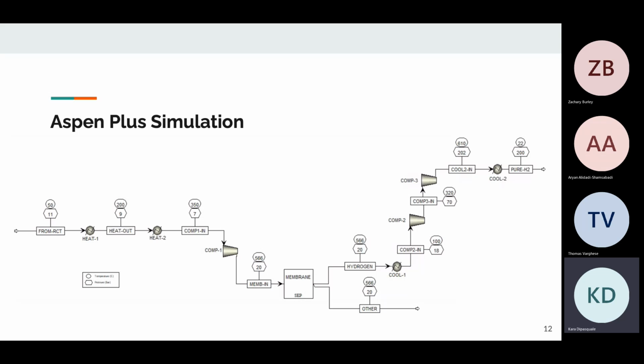Prior to entering the membrane, we heated the streams with a series of heaters to 350 degrees Celsius while obeying the 2-bar pressure drop through each individual heater. From here, we compressed the gases to increase the pressure to 20 bar. The compressor also increased the temperature of the gases to around 566 degrees Celsius, which is optimal for our membrane. Our compressors are assumed to be isentropic, working with 80% efficiency.